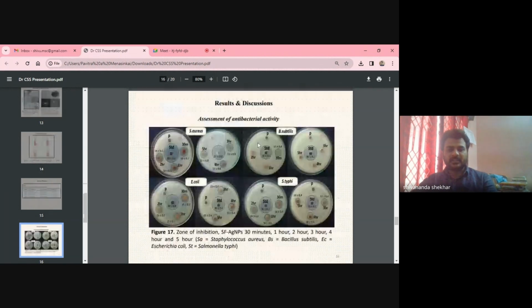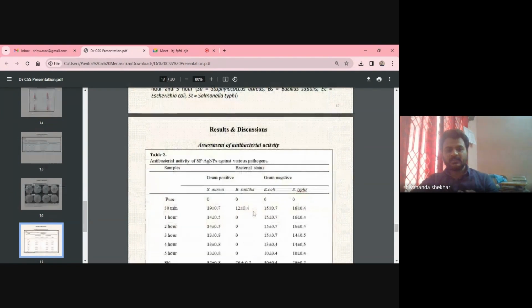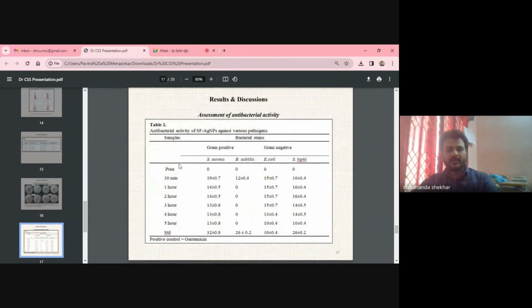And this is the result and discussion for the antibacterial assessment. We tested gram positive and gram negative bacteria and calculated the antibacterial property. We took gentamicin as the standard, and these are the different hours of irradiation. As the hours of irradiation increase, the zone of inhibition also increases. If the nanoparticle size is smaller and smaller, the zone of inhibition is larger and larger. This table shows the antibacterial activity.